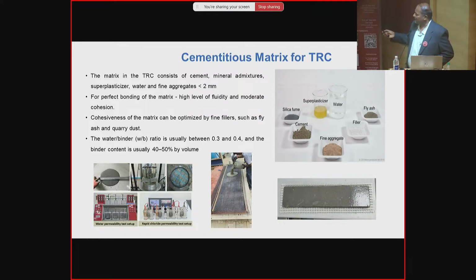So the cementitious matrix, what is the matrix used for this textile reinforced concrete? It is similar to your fiber reinforced ferrocement. Here also we use cement and fine aggregate. The only thing is, the size of the fine aggregate is limited to a maximum of 2 mm, because it has to penetrate through the small grids of the textile reinforcement.